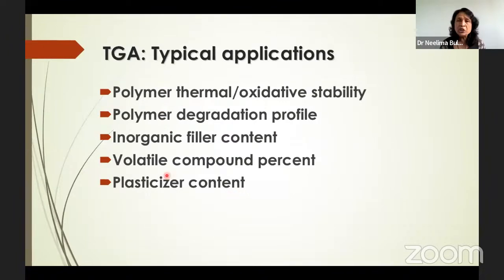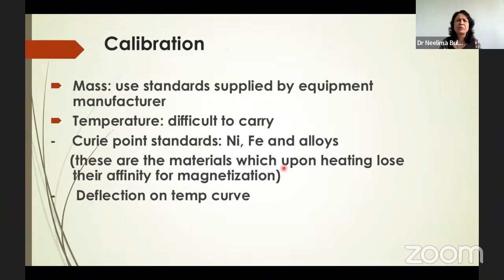TGA typical applications include polymer thermal and oxidative stability and polymer degradation profile, because we have seen the straight curve with residue, without residue, and double steps in TGA. You can find out the inorganic filler content in the material, then volatile compound percent which degrades below 200 degrees centigrade, and plasticizer contents. These are the typical applications people use TGA for.